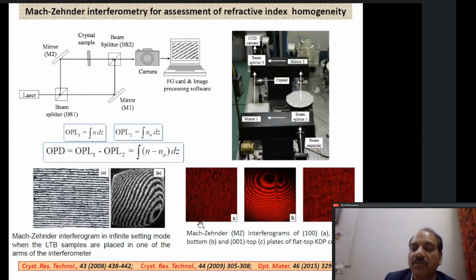And these are Mach-Zehnder interferograms for KDP crystal with a 100 plate, a 001 plate, and 001 top and bottom plates, right? So you will see that here there is a defect. You can see there is a distortion in the fringes here, and the circular fringe pattern is coming because there is a mild curvature in the sample after polishing. And these two, A and C, show equispaced parallel lines which are representative of a very good quality sample.